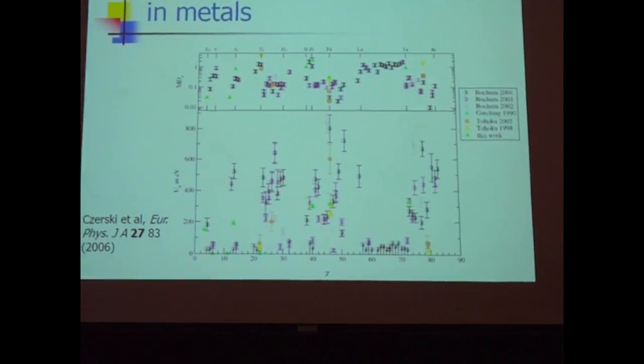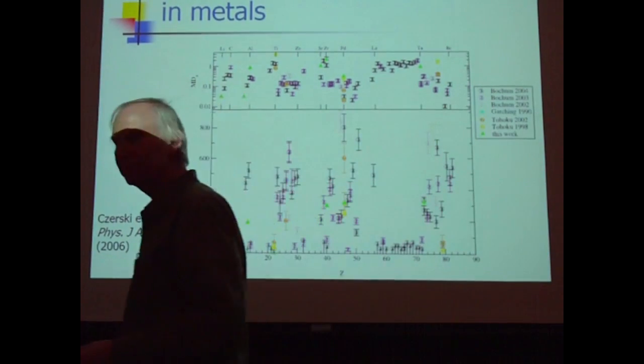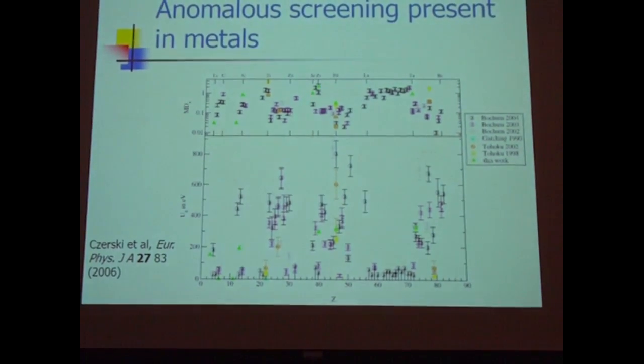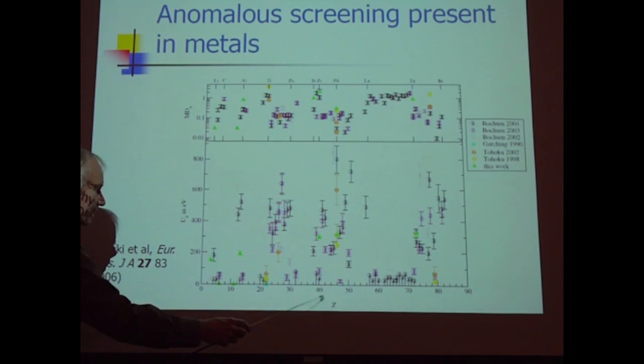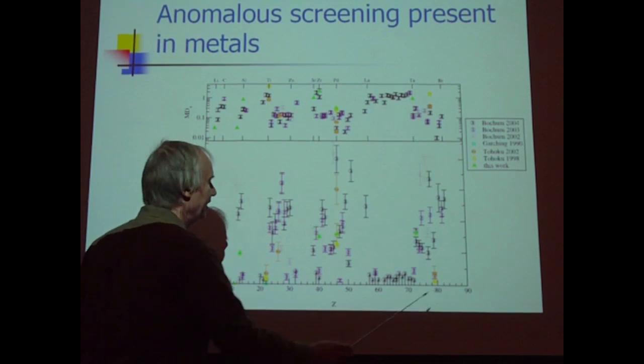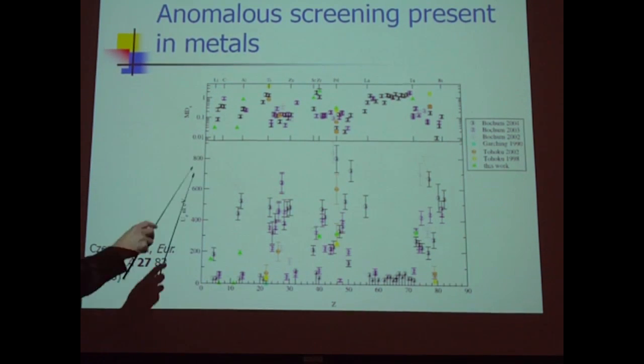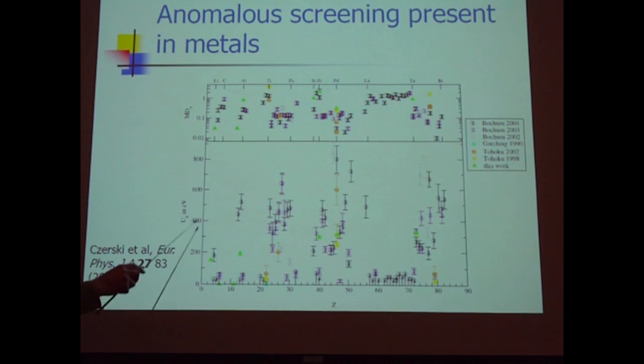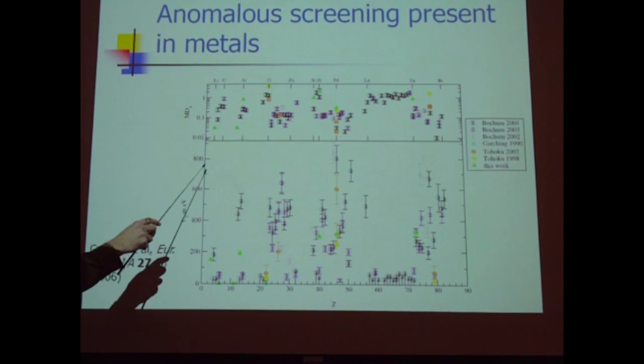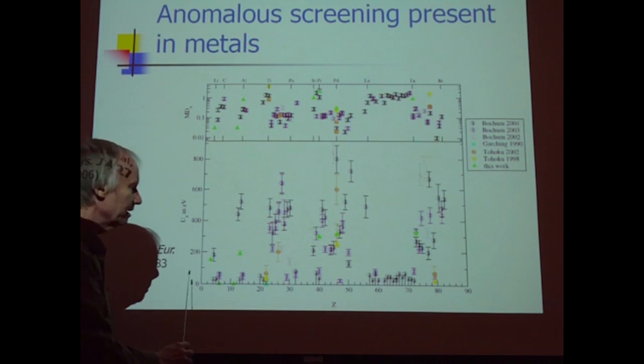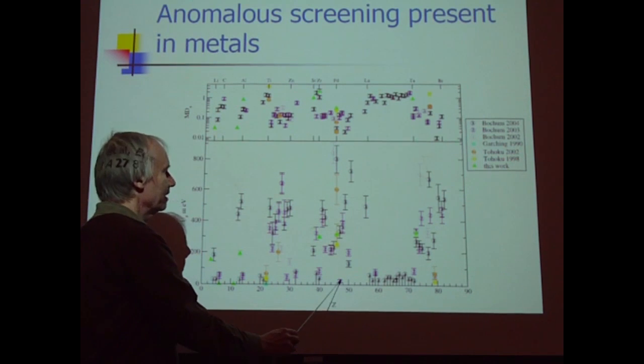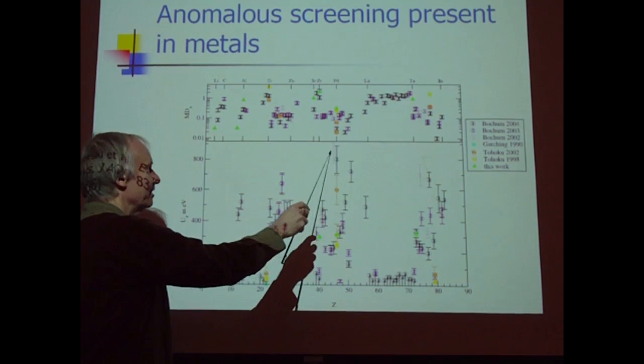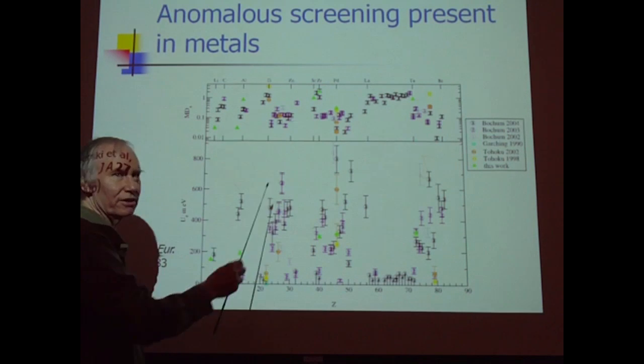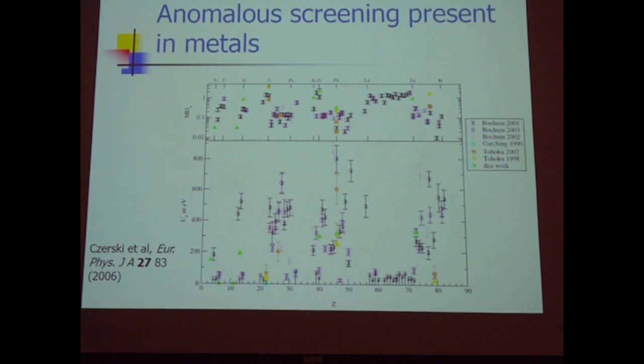Now, over the years, there have been experiments done on lots of different metals. So this is Z, going from 0 to 90. This is the screening energy in electron volts. So here's 0, 200, 400, 600, 800. So if we go to 46 on our dial, there's a lot of experiments, a lot of different energies. The highest ones are near 800, which is consistent with the data that I showed you.